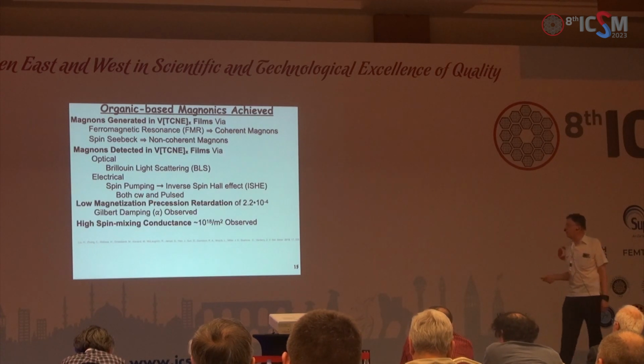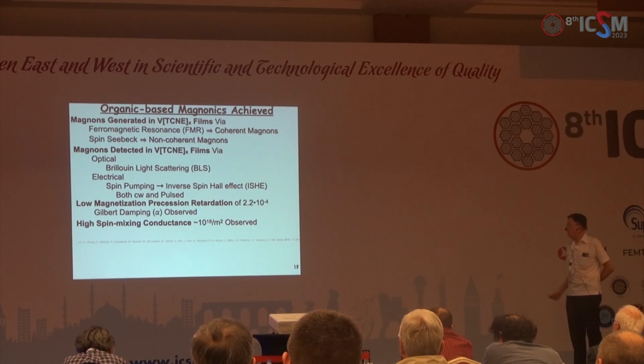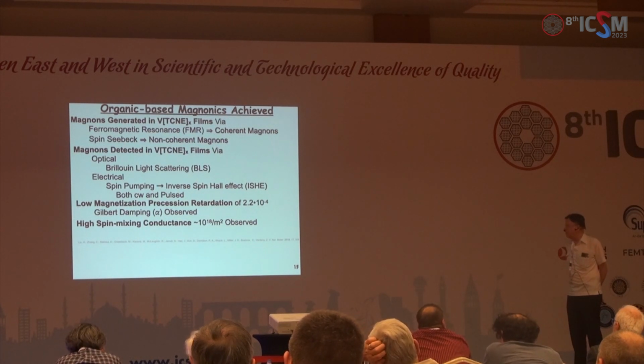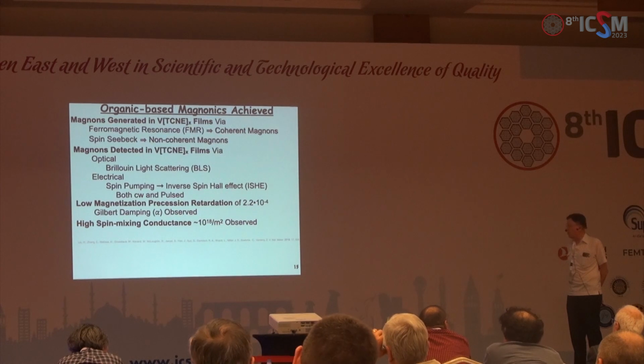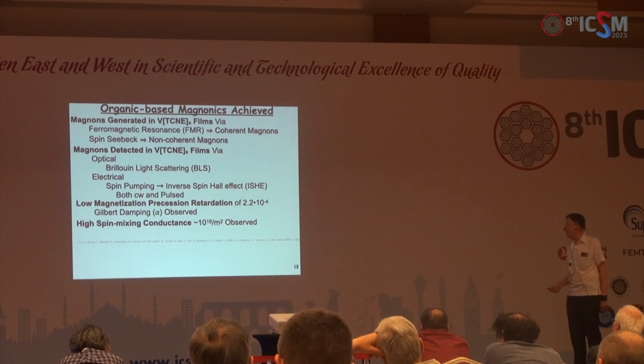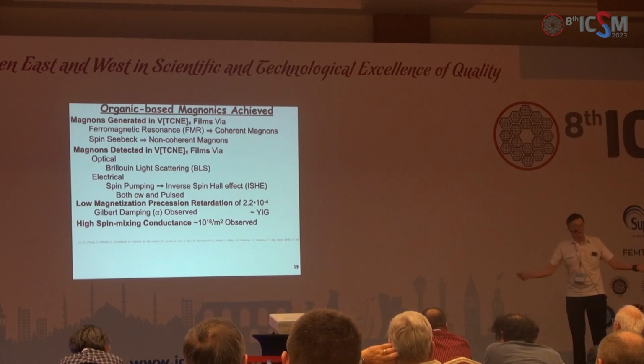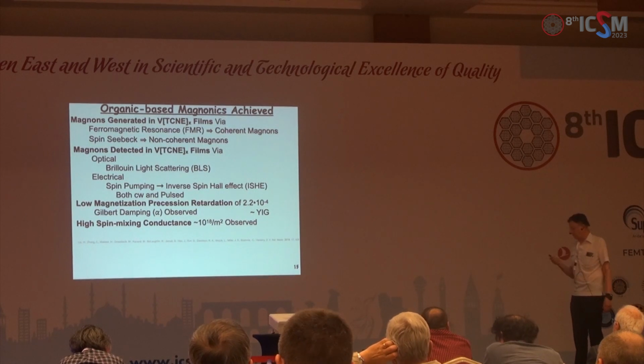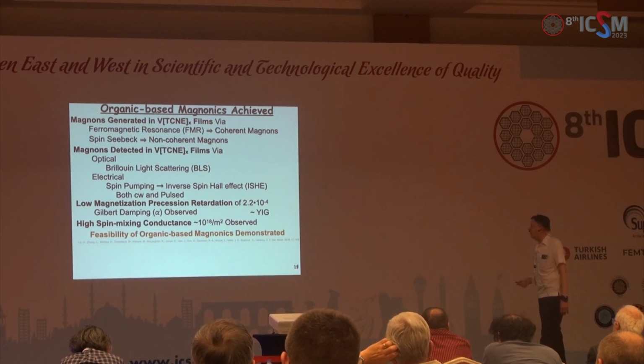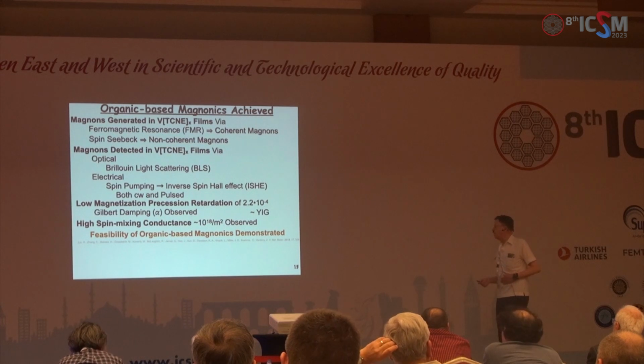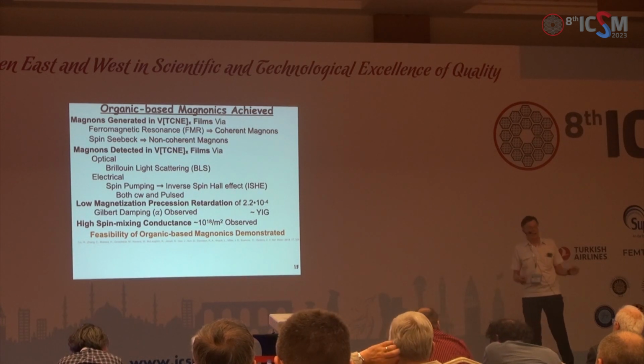We get fairly respectable values for Gilbert dampening and spin mixing coefficients, which are comparable to the YIG benchmark material. So we have demonstrated the feasibility for magnonics using vanadium TCNE.